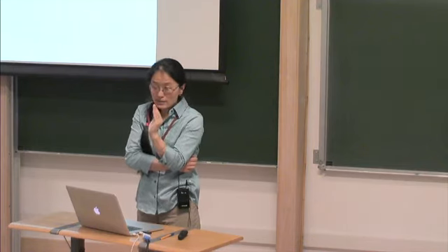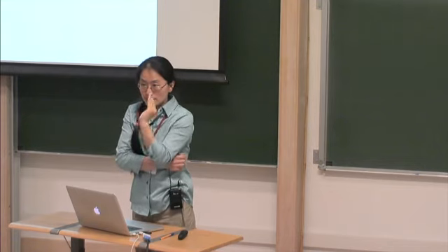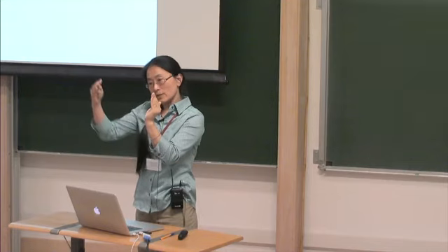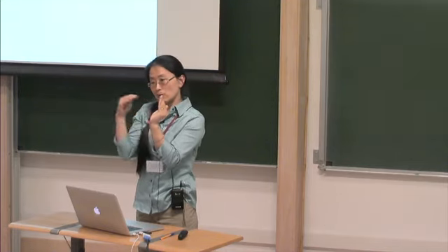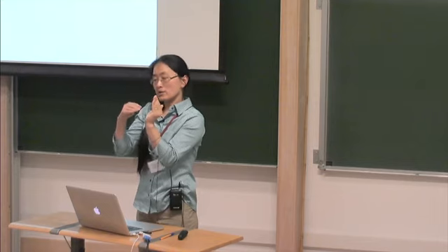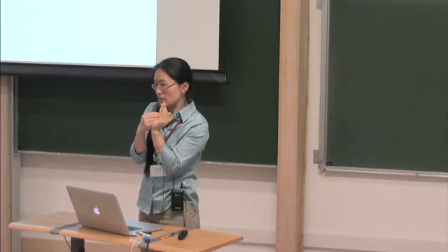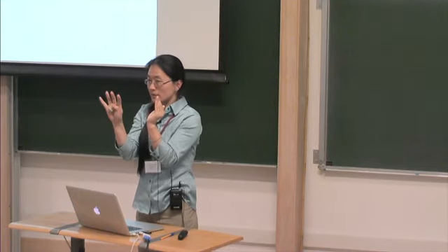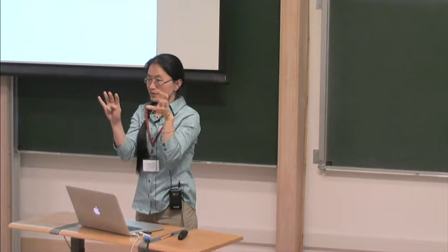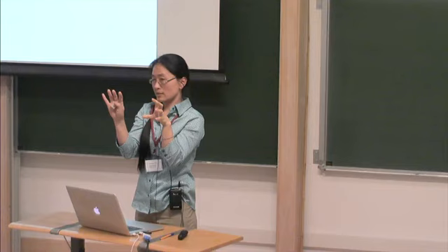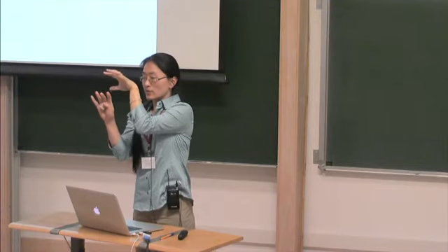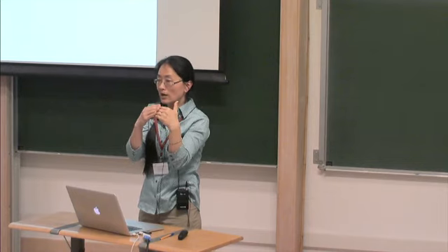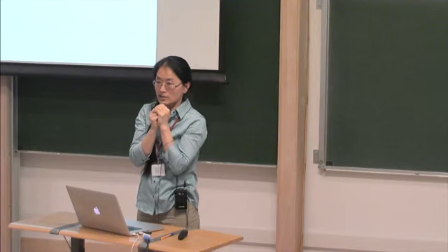And that is for a single-phase system. We relate that to the overall melt. So let's say I put in 6%, the OPX shouldn't cut off yet. But if you have olivine, the OPX doesn't receive 6% because the olivine receives 7%. The OPX only has 4%. So now the OPX are not connecting.